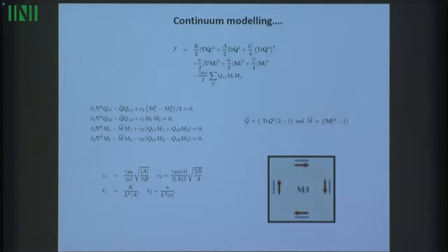And then we are using a continuum approach, so we are postulating, and this is again not original because Alenka Mertelj had a very similar free energy in her paper with her co-authors, but I don't think it's identical. It is slightly different by perhaps one term, but the essential idea is the same. We have a continuum free energy, and there are three different contributions. The first contribution is your usual 2D Landau-de Gennes contribution. The second one is the energy associated with a spatially inhomogeneous magnetization field, and the third one is the coupling energy between the two, between the Q and the M, which somehow enforces or coerces the nematic molecules and the magnetic nanoparticles to line up with each other.